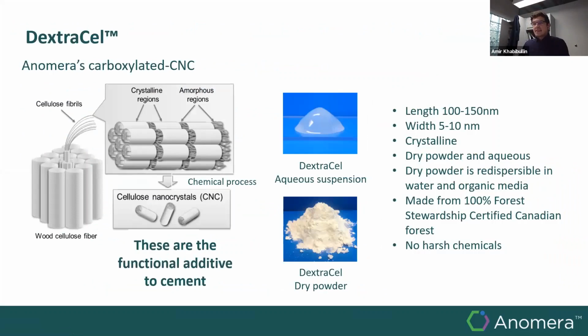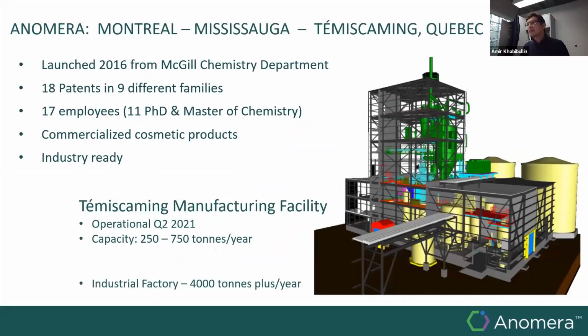We take the pulp and then we apply a chemical process to isolate very rigid, robust crystalline cellulose nanocrystals, which are about 100 to 150 nanometers long and 5 to 10 nanometers in diameter. They could be supplied in aqueous suspension or in a dry powder, which could be easily dispersed in water. As I said, Anomera is a Canadian company.